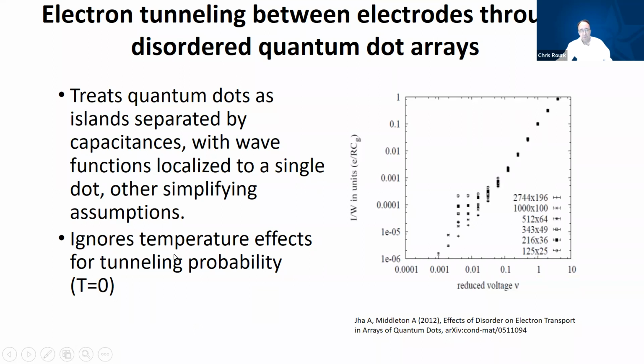I note that he set temperature to 0 to eliminate the effect of temperature on tunneling probability from his analysis, which is not a factor with the ferritin because ferritin has been observed to have room temperature tunneling. But this indicates that the earlier measurements of tunneling through ferritin arrays are consistent with models.